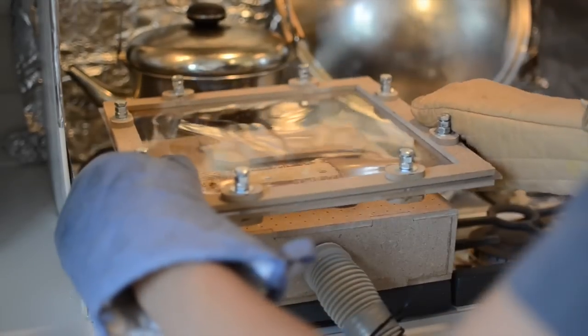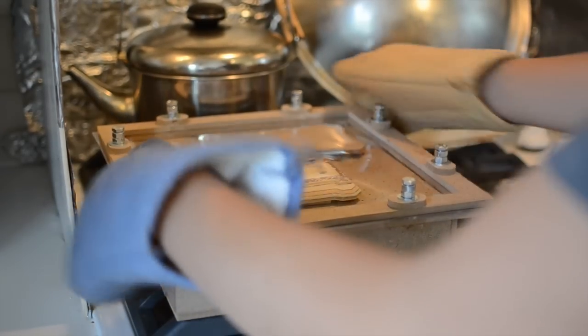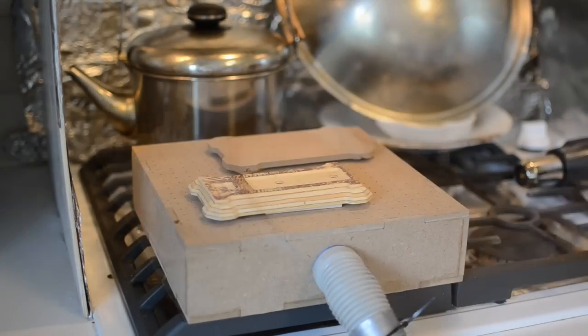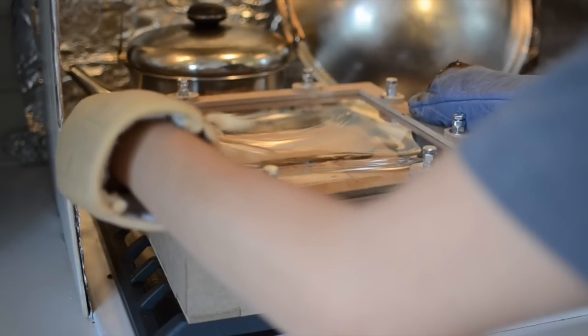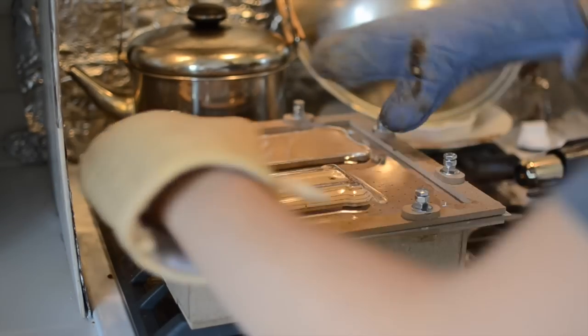When I saw this start to happen, I immediately pulled the frame out of the oven and put it onto the vacuum table. Unfortunately, I was a bit too hasty with this step. The acrylic wasn't soft enough to be drawn over the finer details of my form, so I put it back in the oven to soften further. The next time I tried it, I got further, but it still didn't quite conform to my plywood mold.